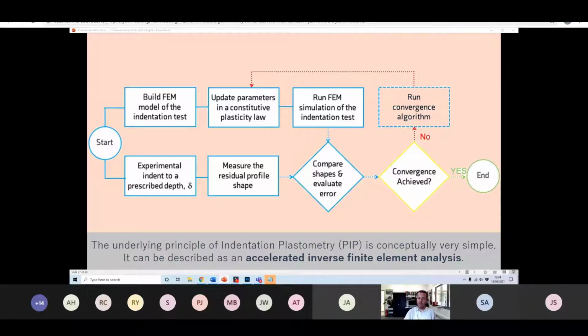Now, like most optimization problems, there are issues of uniqueness to consider, where uniqueness really refers to those situations in which multiple combinations of the input parameters yield acceptably good agreement between measured and predicted profile shapes. But during the course of our research work, we've looked at this in great detail, and we've been able to implement both experimental testing protocols and some computational protocols that allow us to very rapidly identify the unique combination of parameters that are representative of this material. So this framework that we've implemented enables us to converge on the solution very quickly, in just a few seconds. The approach that we're describing here is best described as an accelerated inverse finite element technique.